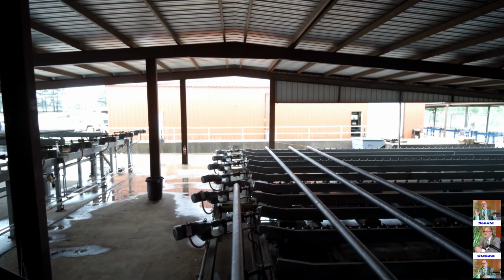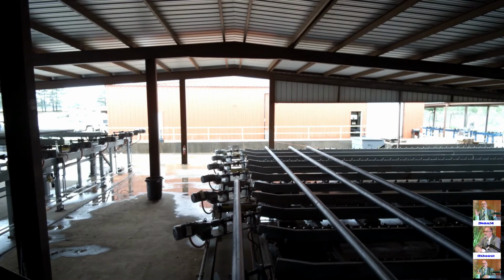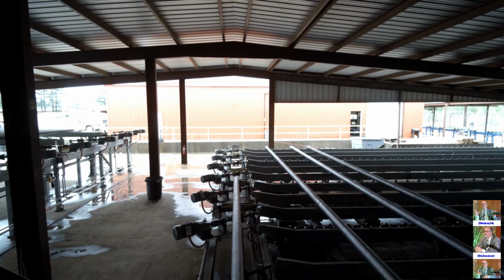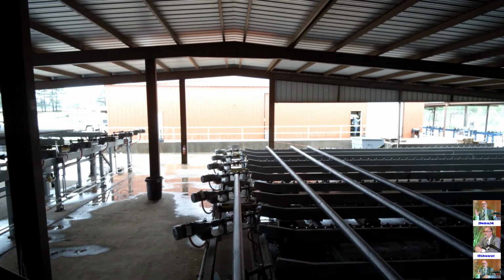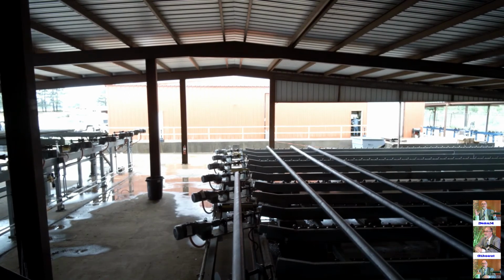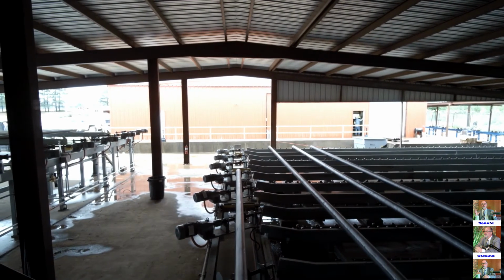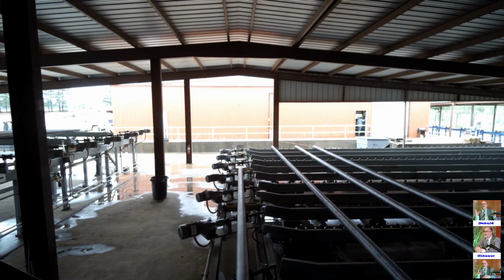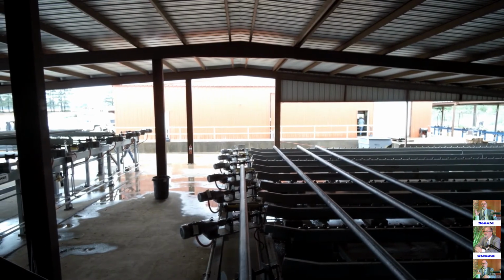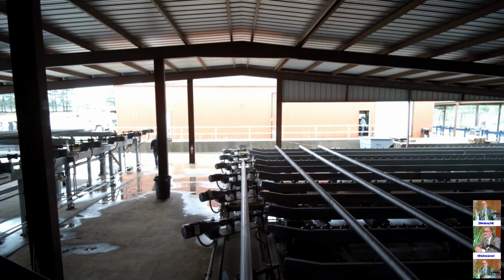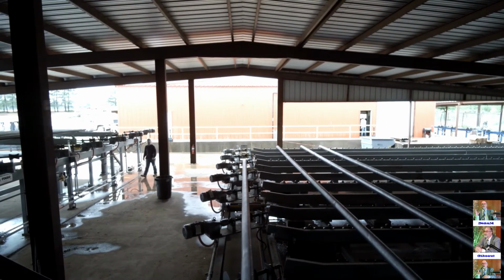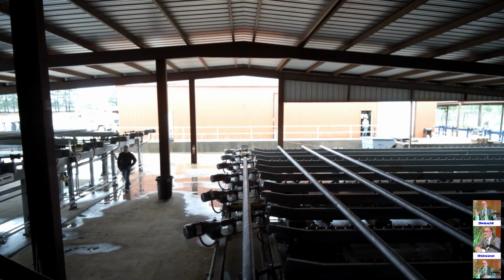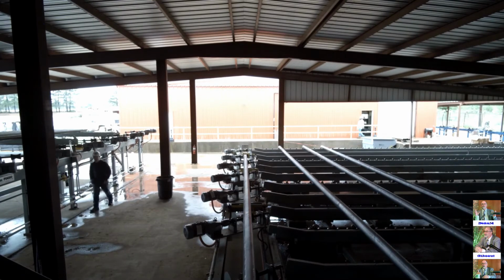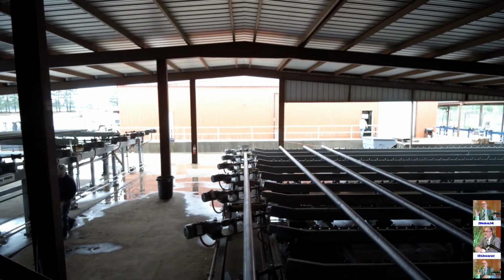Now, you know, this pipe remains hot, so all these rolls are water cooled here on the ID of the shaft. And then it's put onto this drag chain table, and it sits there for hours basically. And again, like we talked earlier, you have to keep it rotating continually till you get down to about 600 degrees, and then you can wrap and cool it.